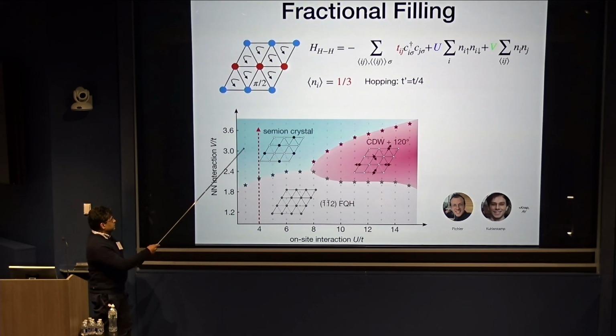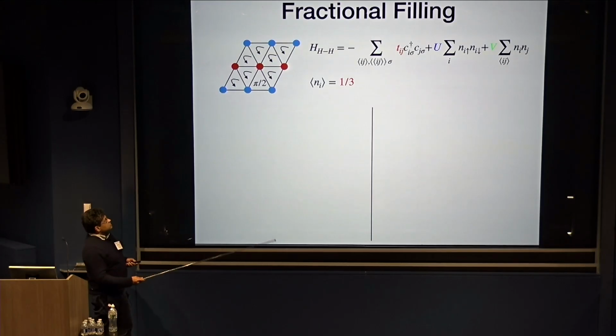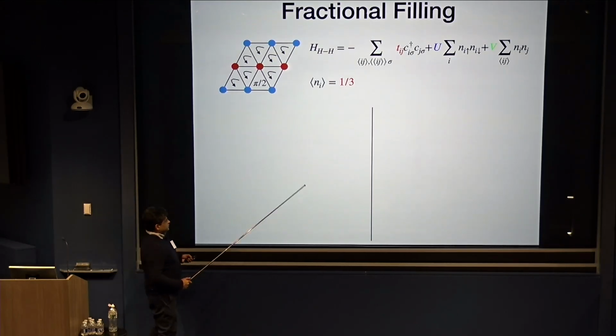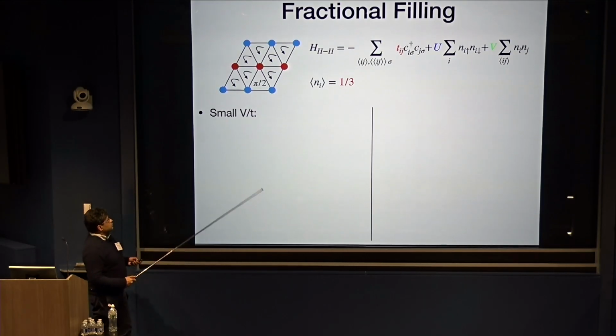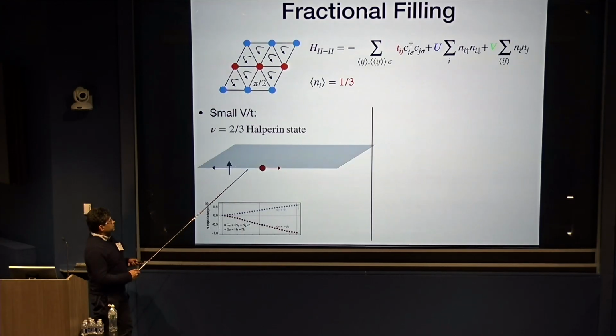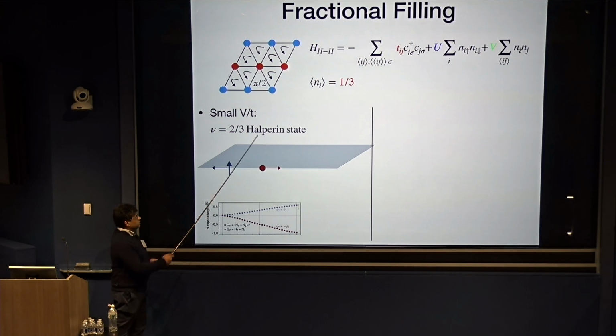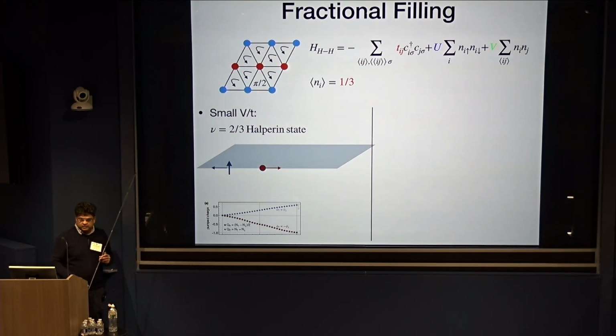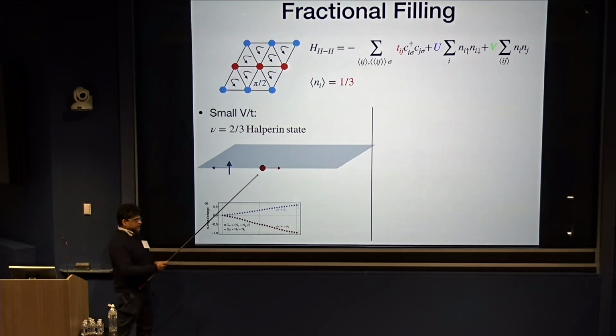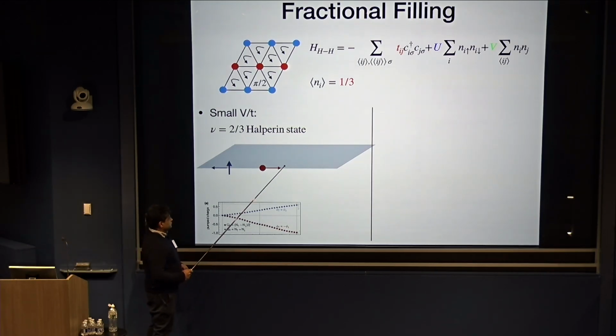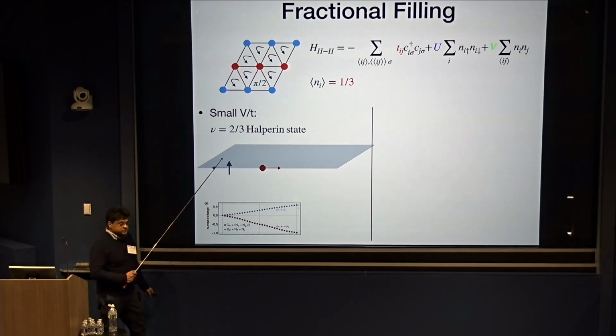When you crank up the interaction V, as you go from this phase to the next. Okay, so this is the phase diagram that you would expect. At small values of V, you get the fractional Chern insulator, essentially a two-thirds filling state with spin, the very natural state called the Halperin state. Okay, and in terms of topological order, it's the same as the usual two-thirds state. It has anyons that carry fractional statistics of two-thirds, but it's nice to enrich it with spin rotation symmetry, which is what happens in this model.